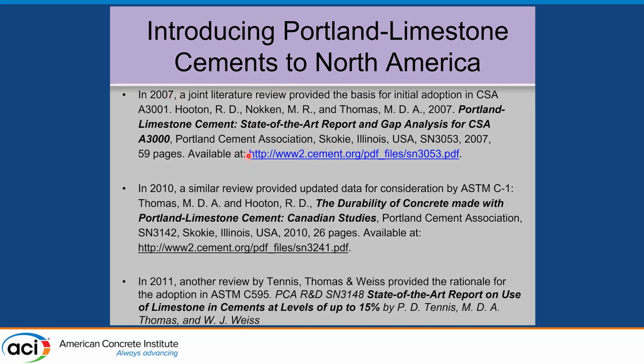It's published as a PCA report. It's still available. And then in 2007, we presented that to the CSA committee. And as a result, we gave qualified acceptance in CSA in 2008 to Portland-limestone cement. The only place where we thought there was not enough information was on sulfate resistance. I'll come to that.